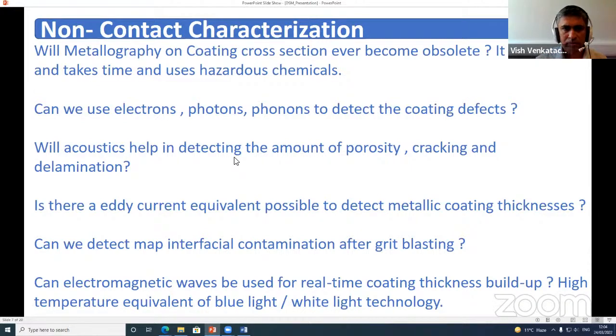Can acoustic technologies, we have some initiative going on at LSBU to determine the health of the coating or the health of the equipment using just acoustics. How to check the porosity or cracking or delamination in the coating using acoustic waves. Can we measure the thickness of metallic coatings with an eddy current equivalent? This is a big challenge in industries currently, where they cannot measure the bond coat thickness without sectioning the samples. So we can contribute on that a lot. And also grit blasting interfacial contamination is a big challenge, and industries are looking for a non-contact solution for that.